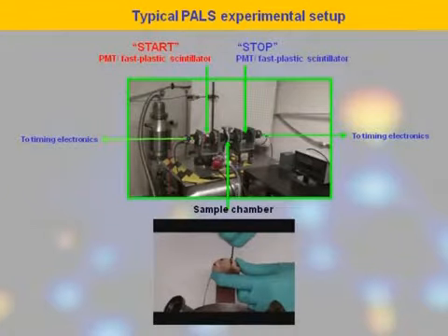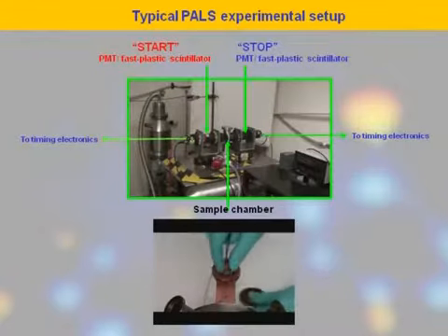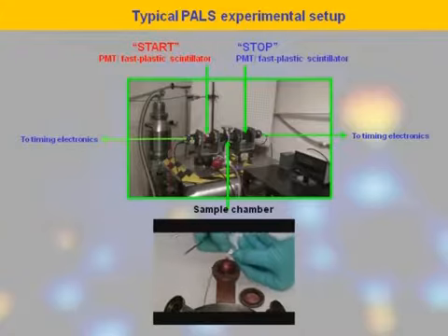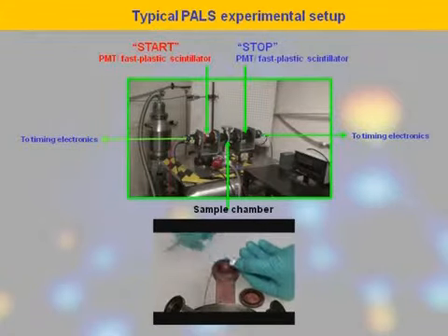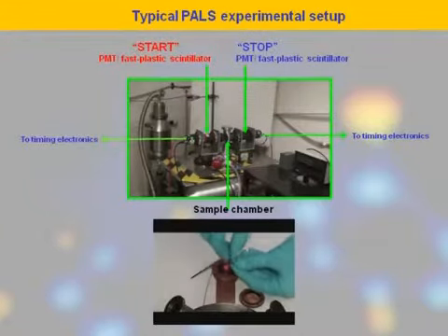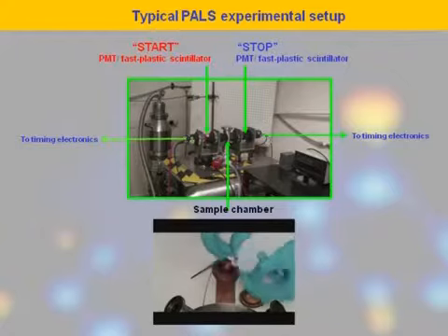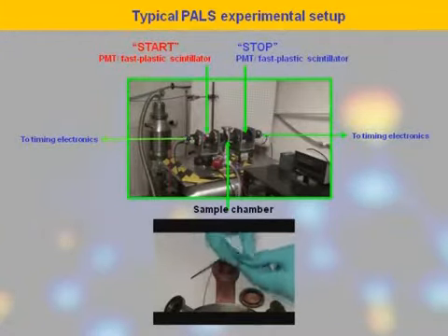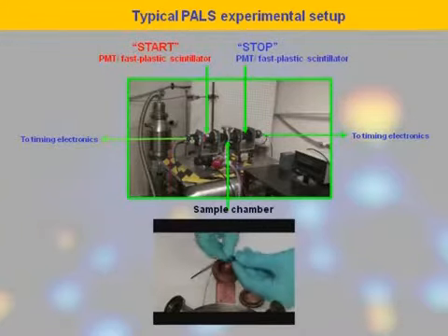For the experiments, gelatin films are stacked to produce a thickness of approximately 1 mm, which is enough to stop 99% of the positrons. Two identical gelatin film stacks are then placed on either side of the source, and the sample source assembly is sealed in an airtight sample holder. With the current experimental setup, we can take measurements in the temperature range of 100 to 430 Kelvin.